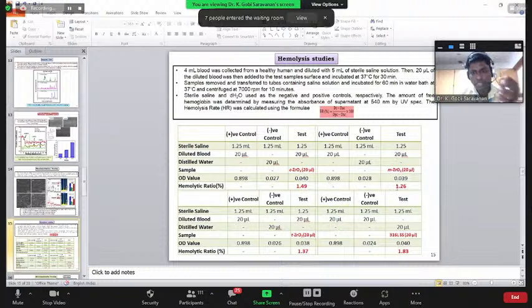So what is the hemolysis? The hemolysis ratio value is there. As per the standard, it should not go beyond 2%. Sorry, this here is the uncoated one, and these are all the coated materials. When compared to the uncoated, the monoclinic shows a very low value, 1.26. So the monoclinic zirconia coating shows a very high hemocompatible nature.